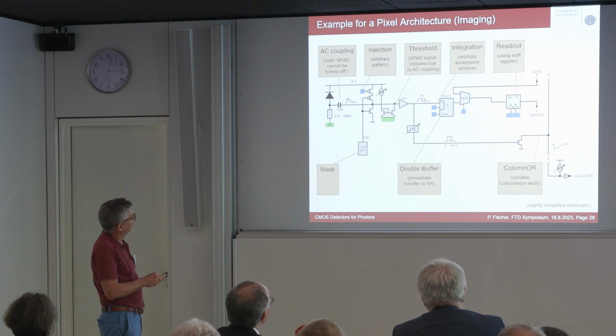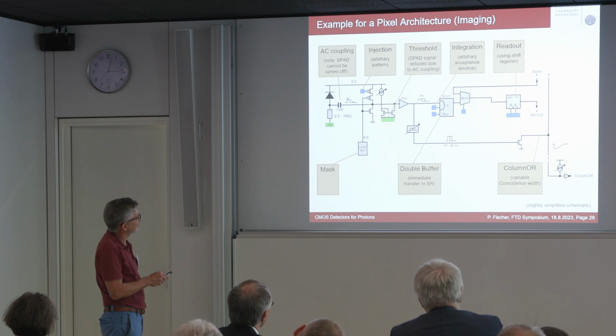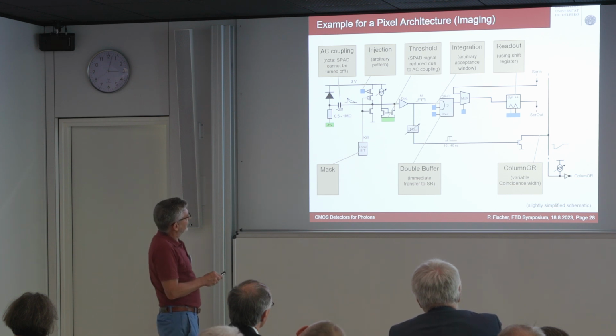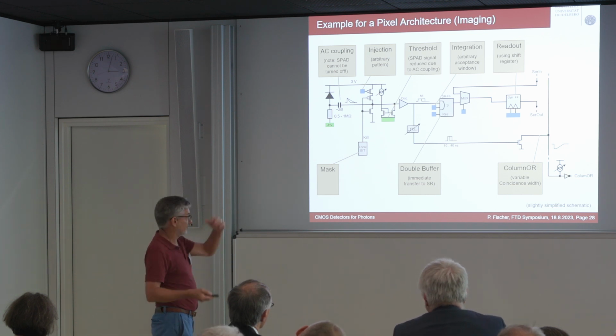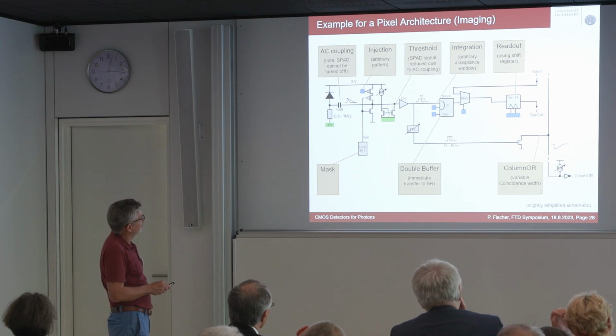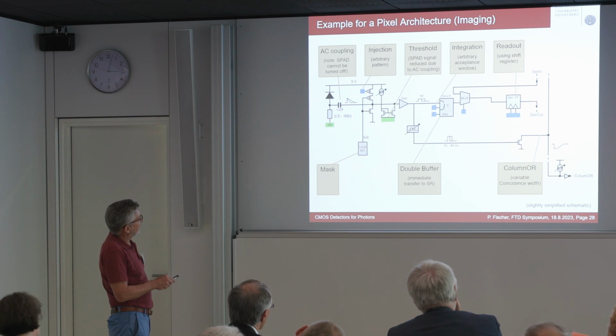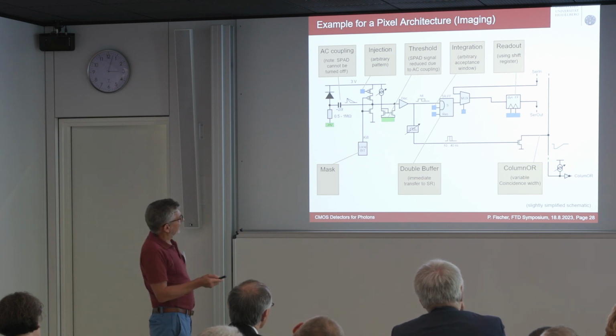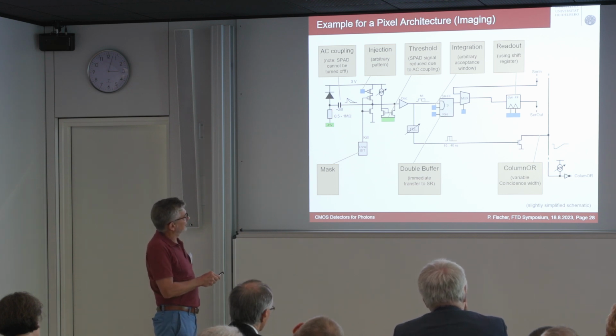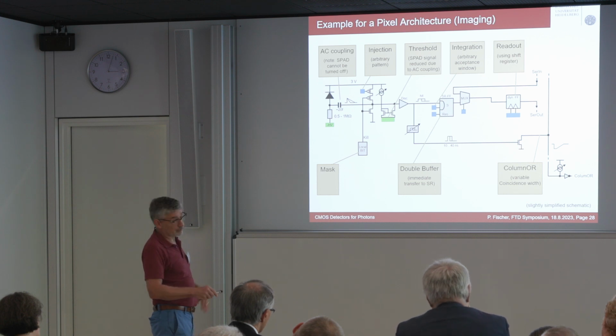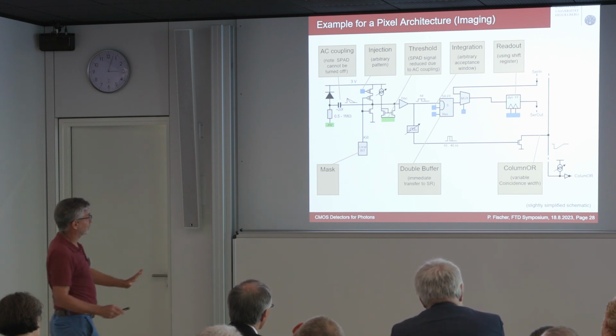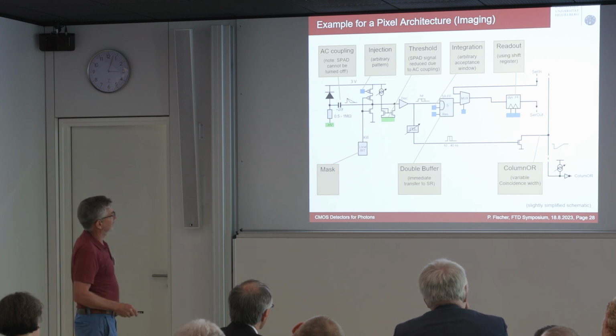We have basically an inverter to make a nice CMOS signal. And then we have a flip-flop, which consists of 6 transistors or so, which we can then set. So we reset the flip-flop before we start. Then we enable here a gate, an AND gate, and when a photon arrives during that time, the flip-flop is set. And when we are done, we load the flip-flop content into a shift register, and we shift it out. Very, very simple. And it should be simple because we want to have fill factor.